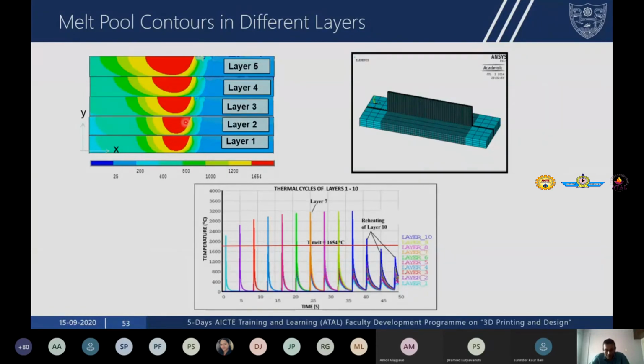Now this poses a challenge because, as I said, we need a consistent melt pool to have consistency in build conditions. Therefore, a number of additive manufacturing processes are using real-time feedback control in such a way that as the melt pool size increases, the process parameters are changed, either power is decreased or scan speed is increased, to maintain consistency in the melt pool.